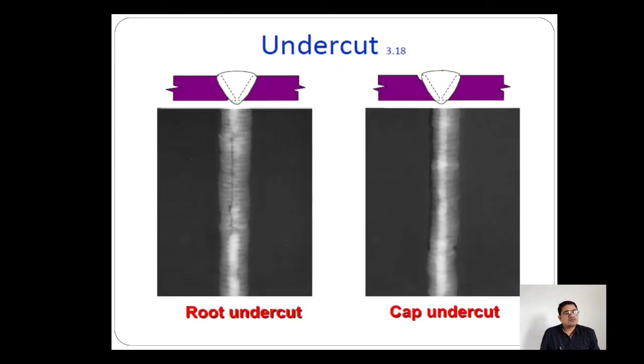So friends, undercut, if you are seeing it in a radiograph, there are two types of undercut shown in this picture. If you refer to the left side, you can see root side undercut is shown. Once a root side undercut is there, you can find in the radiograph, just adjacent to the center of the welding bead, a darker line which shows the root undercut. If you refer to the right hand side figure, you can see the parent metal is melted at the top, and beside the welding bead in the radiograph it is darker, which shows the cap undercut.